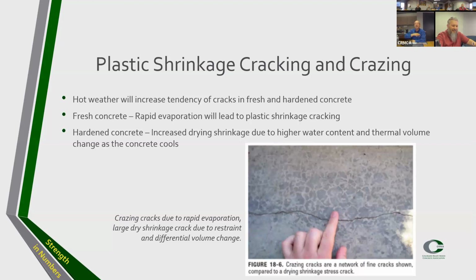Plastic shrinkage, cracking, and crazing. Generally, hot weather, hot concrete, will increase the tendency for cracks in fresh and in hardened concrete. In fresh concrete, it's generally because of the rapid evaporation of the water that leads to plastic shrinkage cracking. Hardened concrete, it's just drying shrinkage, especially when we have higher water content. What we showed before, you have higher shrinkage and there are cracks that might develop. So in this case, you see the crazing cracks because of the rapid evaporation, and then a large dry shrinkage crack that just formed later on in the concrete.